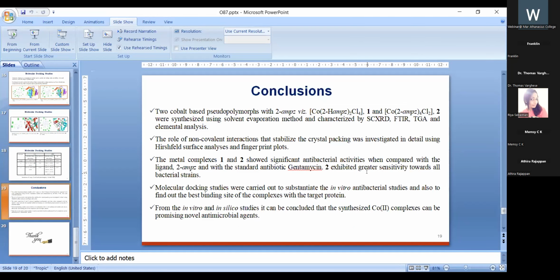To conclude, two cobalt-based pseudopolymorphs with 2-aminopyrazine ligand were synthesized using the solvent evaporation method. The role of non-covalent interactions that stabilize the crystal packing was investigated in detail using Hirshfeld surface analysis and fingerprint plots. The prepared complexes showed remarkable antibacterial activities when compared with the free ligand and the standard antibiotic gentamicin. In particular, 2 exhibited greater sensitivity towards all bacterial strains.